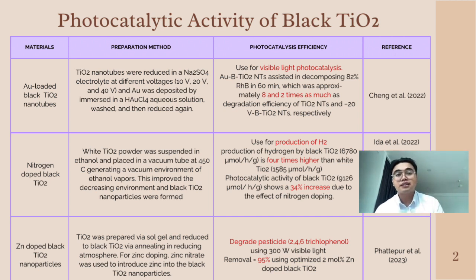And the last synthesis method is zinc-doped black TiO2 nanoparticles. It is used to degrade pesticide using 300 watt visible light, and it shows significant effect, with removal of 95% using the optimized 2 mole % zinc-doped black TiO2.